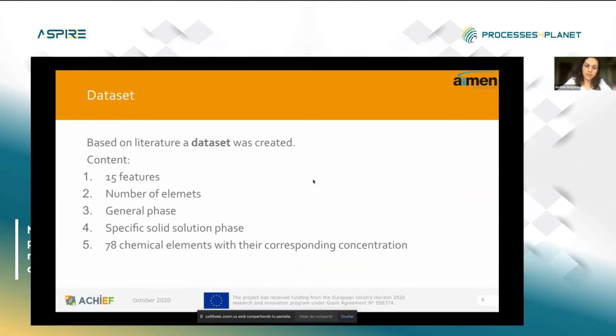Concretely, focusing on the first step, the dataset ended with more or less 1,000 high entropy alloys, which were found in literature. Each alloy has 15 related physical features that describe its behavior. Then a column with the number of elements that each alloy contains. Its general phase, which, as I have said before, can be solid solution, intermetallic, amorphous, or a mix of them. In the particular case of the solid solution ones, its specific solid solution phase was also specified, which could be, for example, FCC or BCC structure. And finally, 78 chemical elements were taken into consideration to be part of the final alloys. So they were included with their corresponding concentration for each alloy.